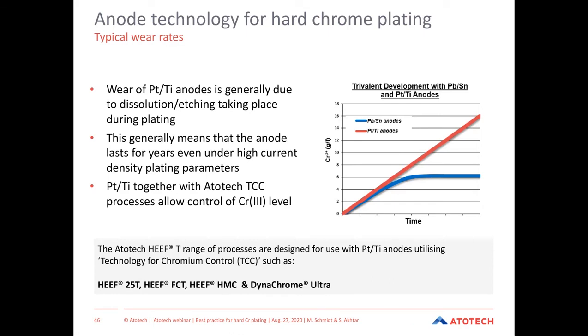The platinized titanium anodes are also wearing. The platinum layer is reduced during operation, which basically means the lifetime has an end. Typically, lead-tin anodes are changed every 1 to 2 years. Platinized titanium anodes last definitely longer. Usually the lifetime depends on the current applied and on the throughput. It's between 3 and 7 years, also depending on the platinum thickness of the anodes.